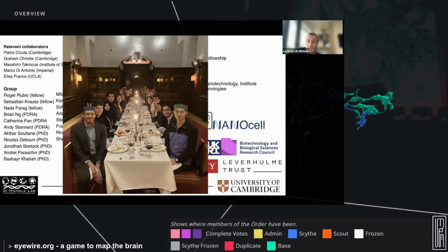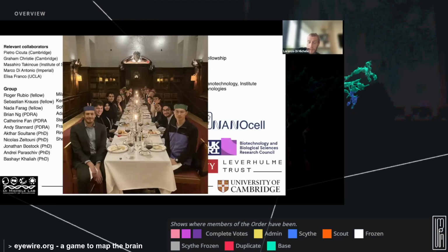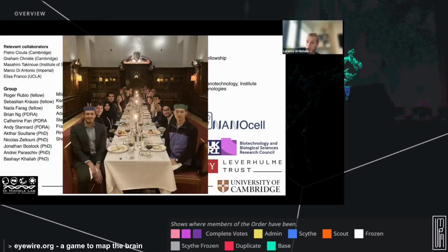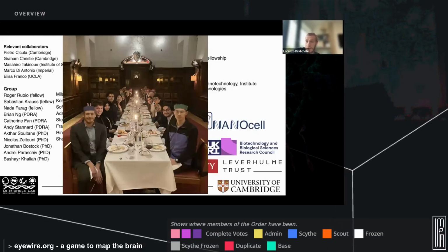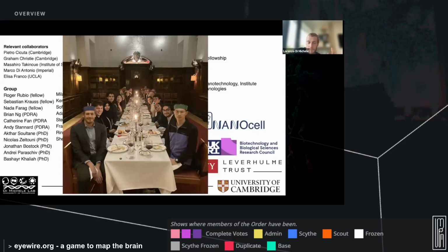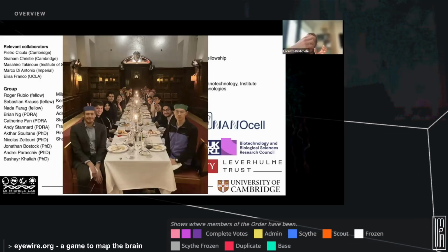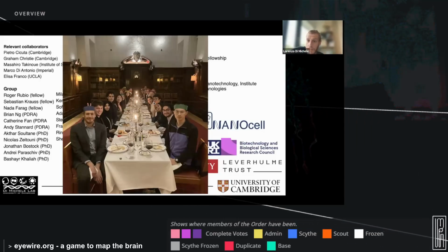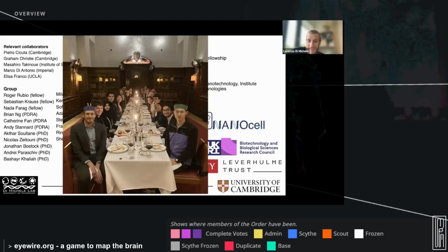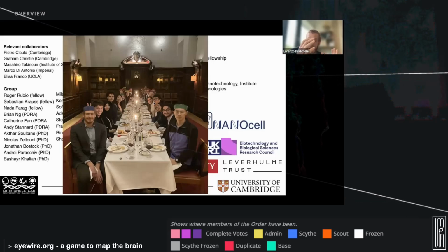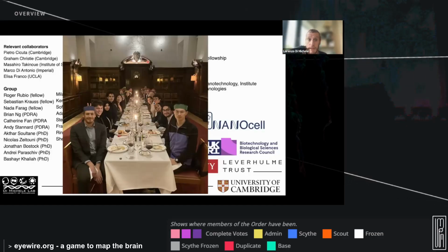For the DNA condensates, because you can leverage chemical modifications, then you can do all of this and more. So people have demonstrated that these DNA condensates in vitro can assemble in response to certain cations, antibodies, and you can use, for example, azobenzene modified oligos to make them light responsive. And I'm sure I'm forgetting some of these very cool results. There's a vast literature, and this can be done definitely, and can be done repeatedly.